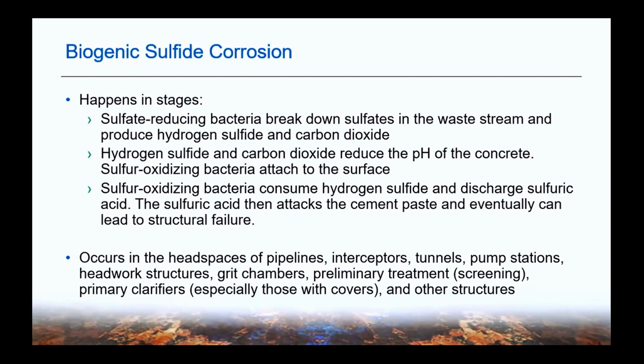What you end up with is sulfur oxidizing bacteria that end up consuming hydrogen sulfide, and they end up excreting or discharging sulfuric acid. And this sulfuric acid has actually been measured at a pH of less than 2. But the highly alkaline cement paste in the concrete matrix is very susceptible to attack from that low pH acid. And so if you're not paying attention, or if this goes undetected, I've seen this cause concrete degradation up to 2 inches a year. So it can be catastrophic. And it's one of those things with underground assets, and maybe assets that you're not looking at all the time, it can act very quickly.